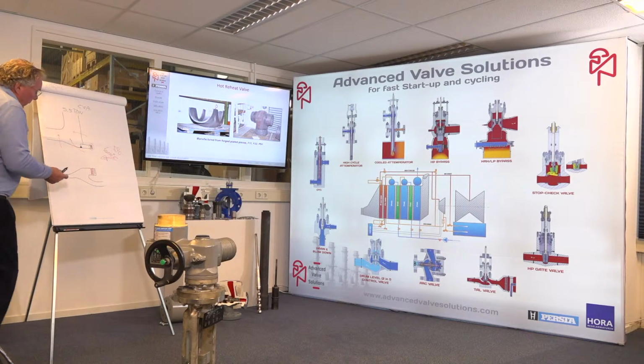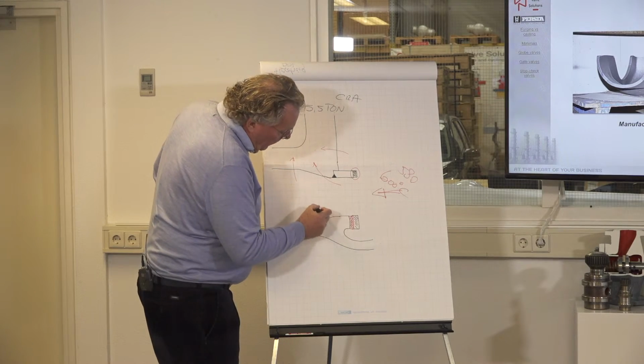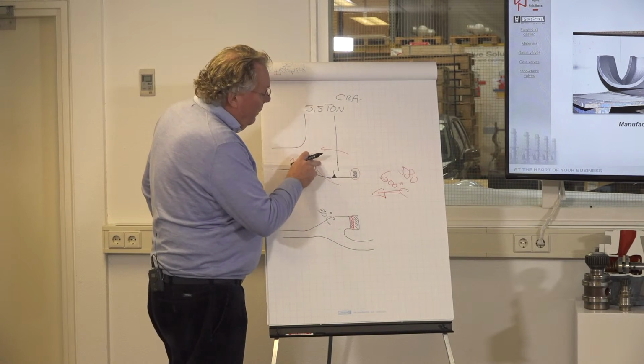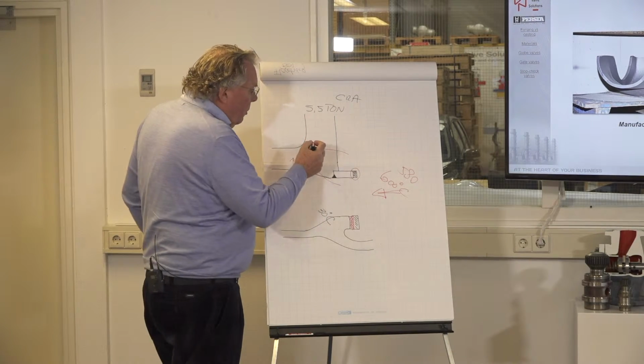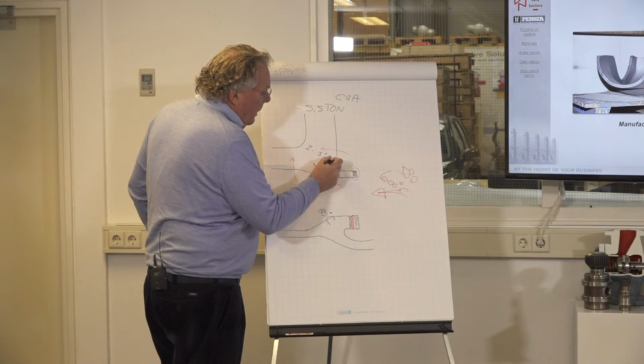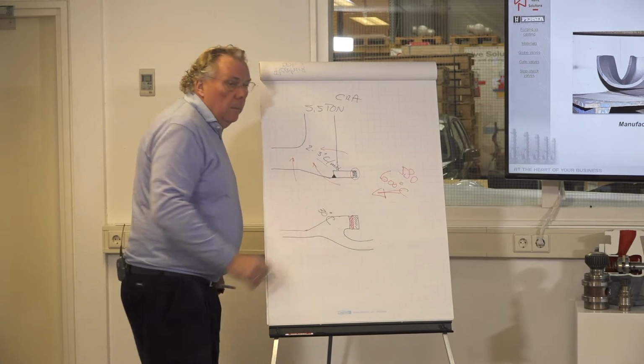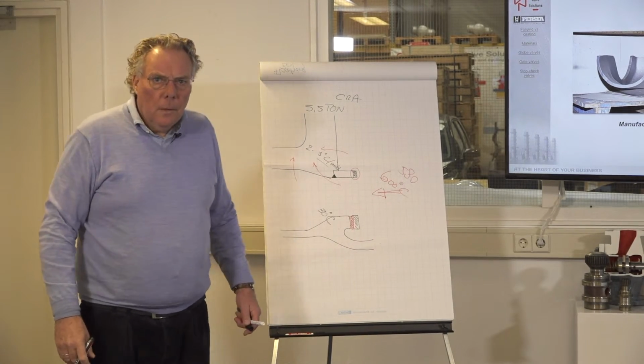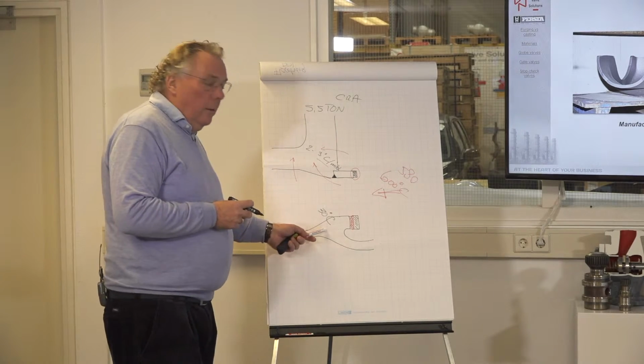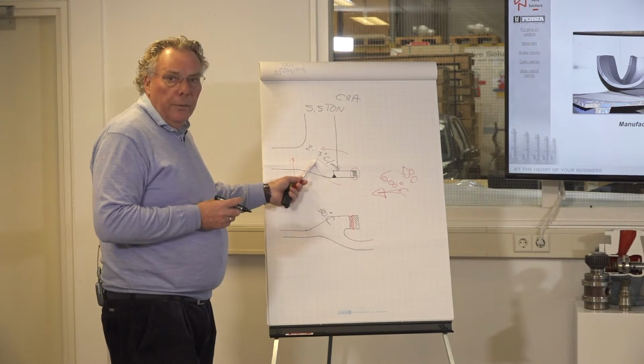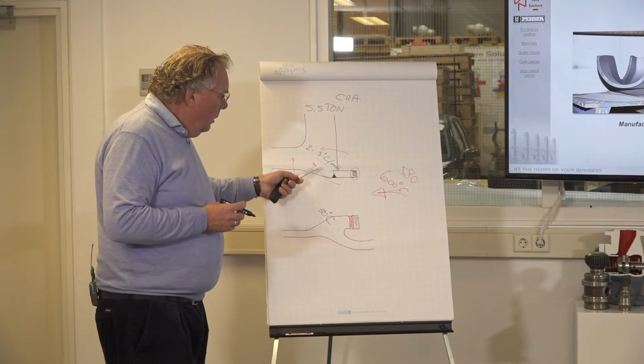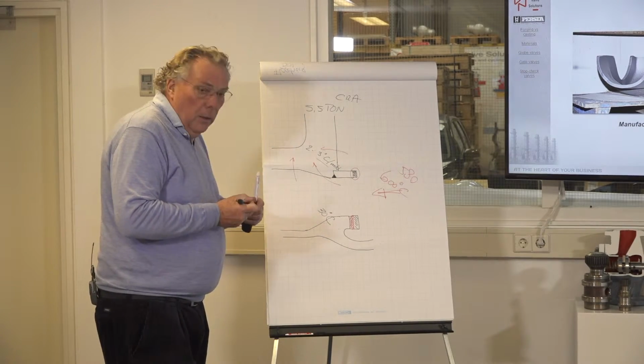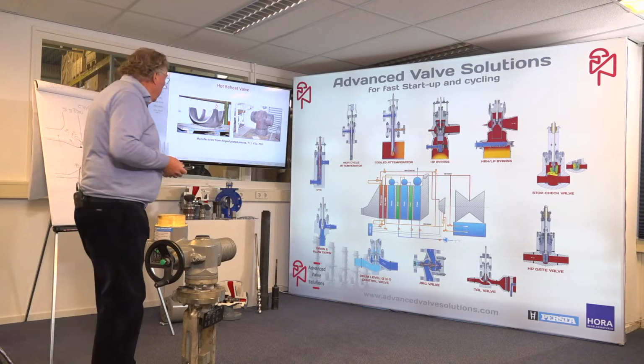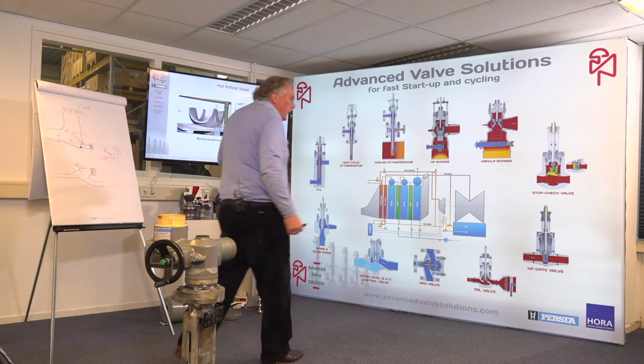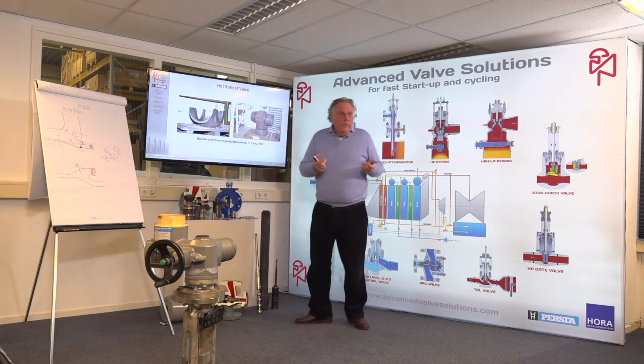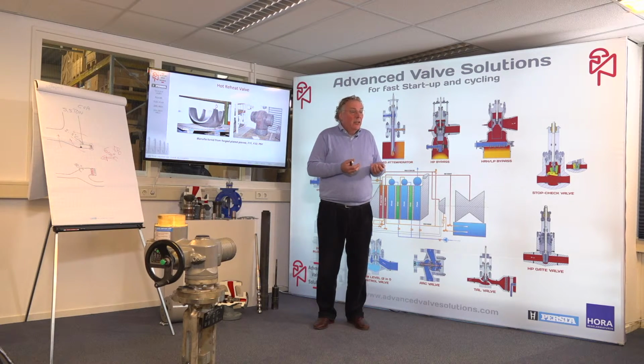So this design valve can ramp up with 30 degrees C per minute. The old design valve is basically 2 to 3 degrees C per minute. Well, that is a fundamental difference. Consequently, these valves don't fail, those valves will fail. This is the construction of basically a high ramping up main steam stop valve, but it is also the construction we use in the hot reheat valve, because the hot reheat valve does have exactly the same problems.